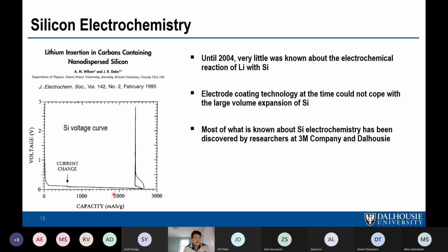And this is just a conventional PVDF coating, I think, or maybe EPDM back then, I can't remember. And you can see what happens. With a conventional coating and a conventional electrolyte, you can lithiate silicon almost to its theoretical capacity, but when you try to delithiate it, you can't take any lithium out. And so before you can learn anything about the electrochemistry of silicon, you have to improve the situation. You can't learn anything from this.